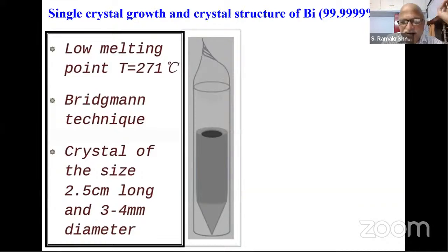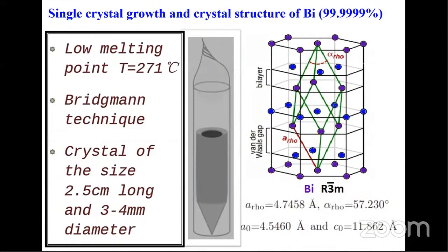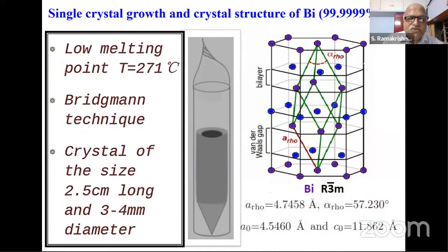Okay, so now let me go to the practical points. Bismuth can be grown very easily. It can be grown in air by just pulling it out of the heat. You have a small furnace and a small motorized pulley, and you can pull it out slowly. In fact, you will see nice crystals with shining colors, which is basically an oxide that gives you interesting colors. But for our experiment, we need 6N pure bismuth, that is 99.9999% pure bismuth. So it has to be grown in vacuum, and that is what is done in Professor Tamilpay's lab, where we grow these crystals.